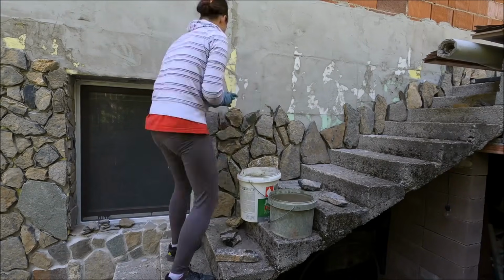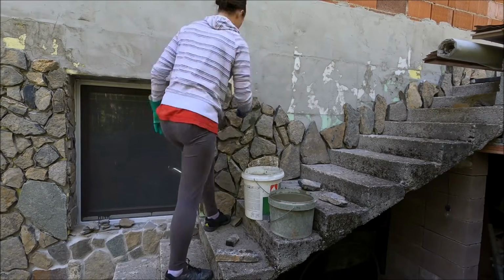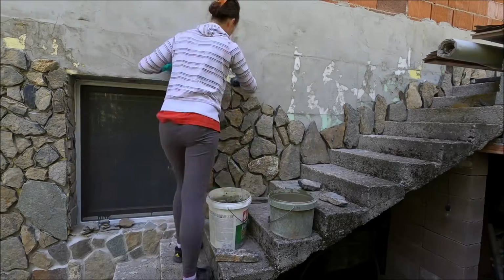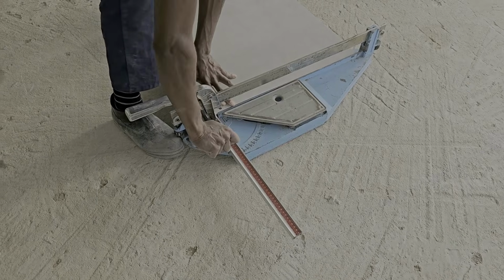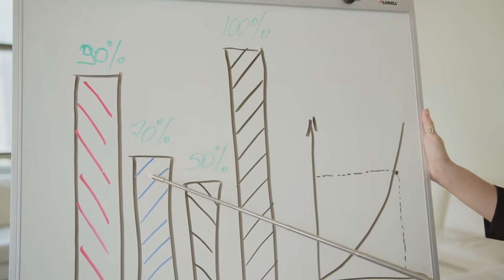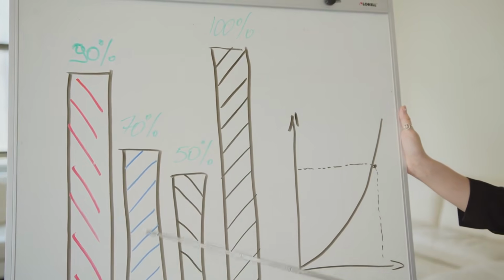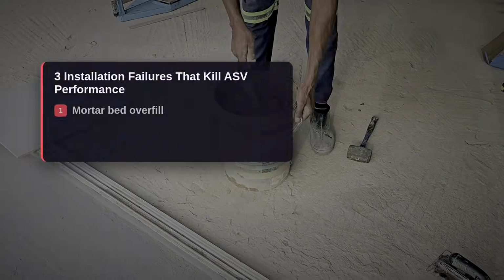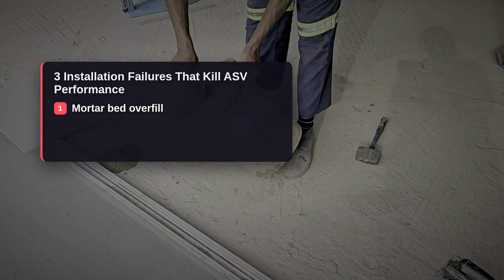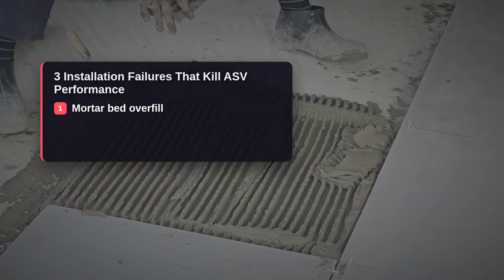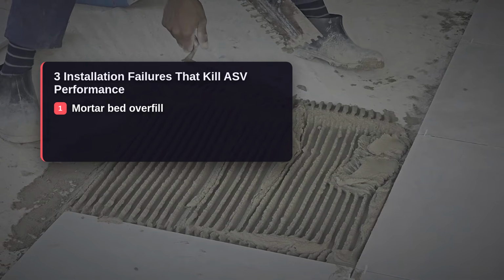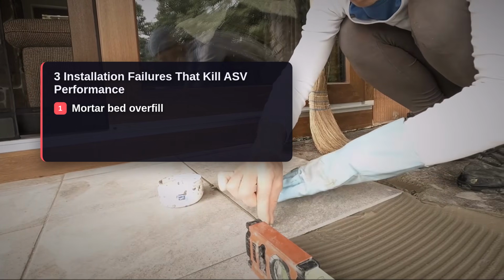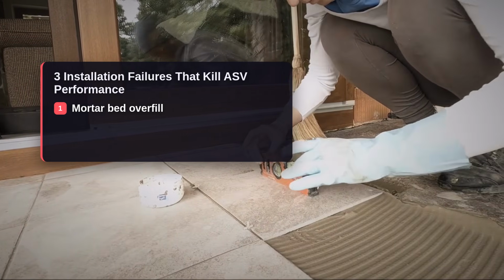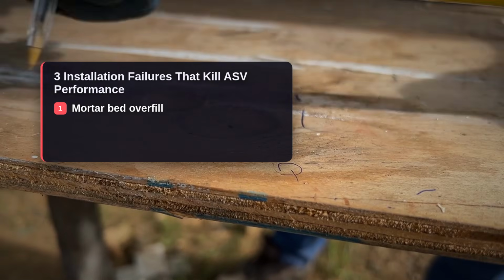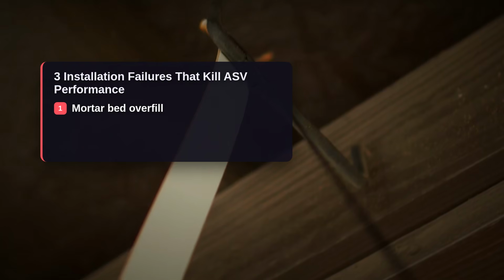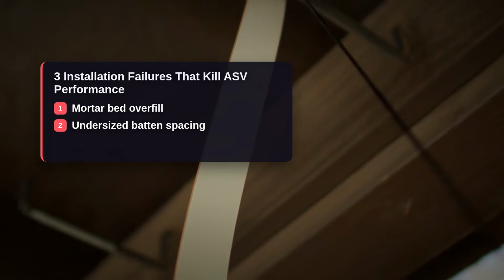Let's get specific about installation quality, because this is where the actual performance numbers get compromised or confirmed. The Florida Solar Energy Center data, showing a 48% heat flux reduction, is based on a correctly installed system with a continuous, unobstructed air channel from eave to ridge. 3 things commonly go wrong in the field that destroy that performance. The first is mortar bed overfill. Some installers, following old practice or trying to speed up installation, fill the air channel under the tiles with mortar at regular intervals rather than only at the hip, ridge, and eave ends. When that channel is filled, the ASV mechanism stops. You lose the ventilation entirely and are left with only the reflectance and mass benefits, roughly a 20 to 25% improvement instead of 48%.